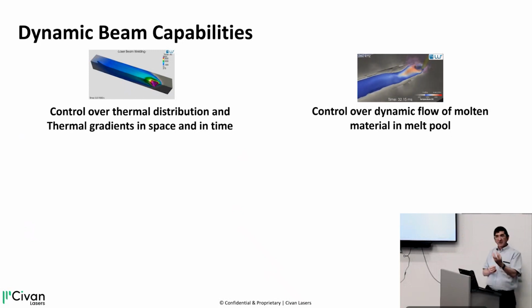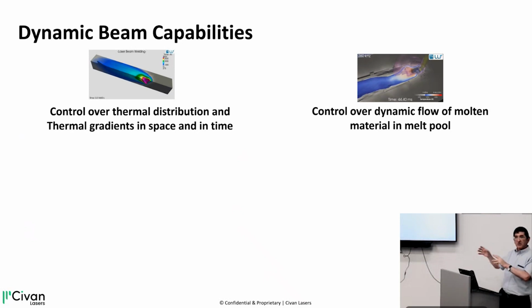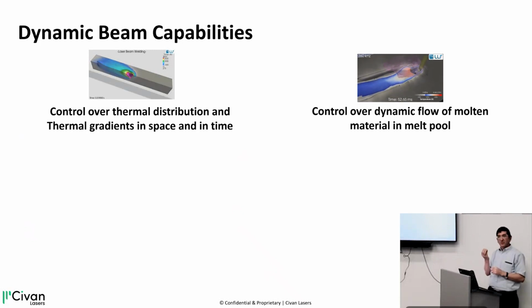And because we have the melt pool, and inside the melt pool we have the keyhole, and the keyhole is gas with high pressure. It creates forces on the molten material and pushes the molten material. And we can move the keyhole, create a few keyholes, move the keyhole from place to place and so on, so we can actually create flow of molten material inside the melt pool.